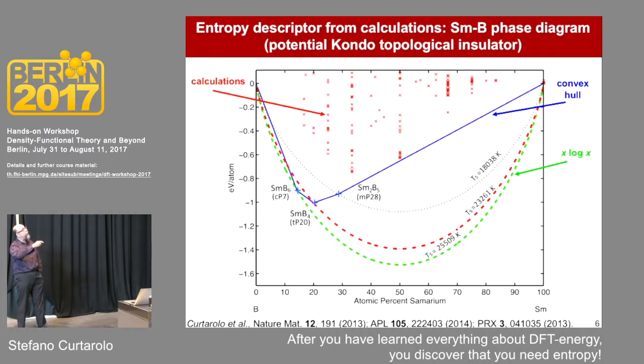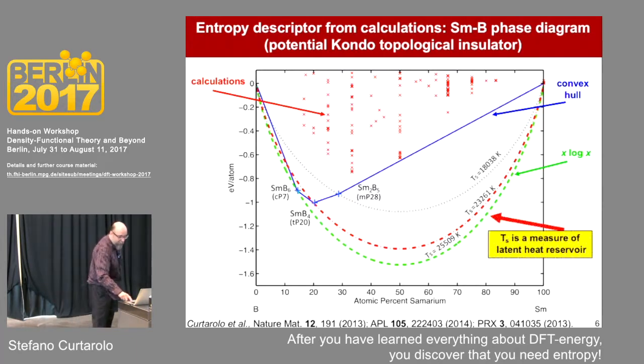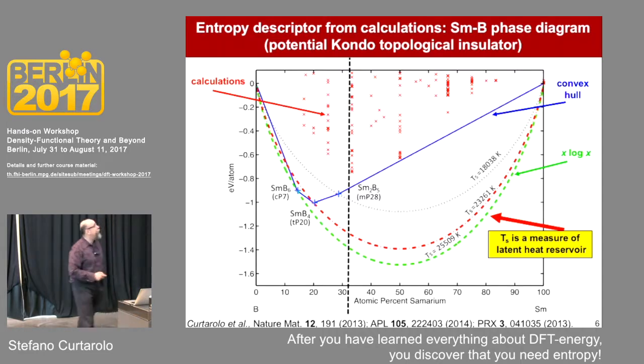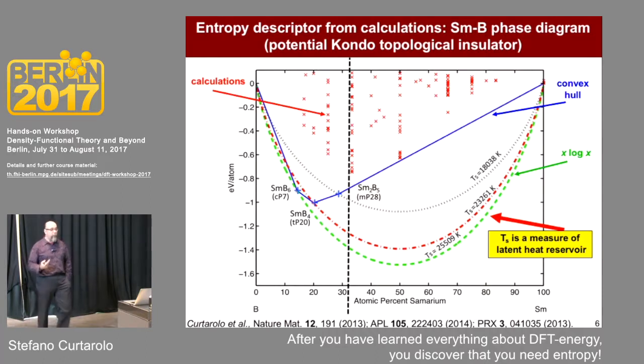Okay, so you see that samarium boron 6 is here, samarium boron 4 is here, and the other one is here. Since the chamber works at low temperature, zero temperature, and you are in the grand canonical ensemble because you have plenty of gas and can recombine at will, you should really minimize the free energy, okay? So if you start from this concentration, you should go down in formation energy, hit the blue line, go to this point, and eventually go to samarium boron 4. So if you follow blind thermodynamics from the grand canonical low temperature, you would get samarium boron 4. But this is not what happens.